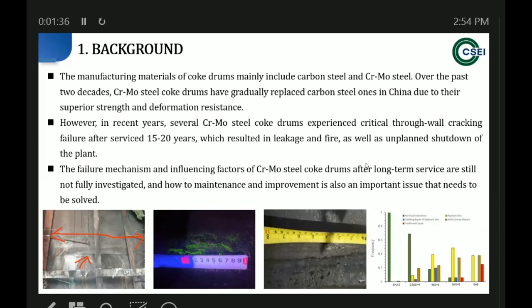However, in recent years, we have found this kind of coke drum experiences critical through wall cracking after 15 and 20 years. It sometimes results in leakage, failure, and unplanned shutdown of the plant. So we are very concerned about the failure mechanisms and the influence factors of such coke drums. There is also some research, especially in the US, such as API 934G, with many data, but we have no such data in China. So we did this study to know how to maintain it and improve this failure problem.